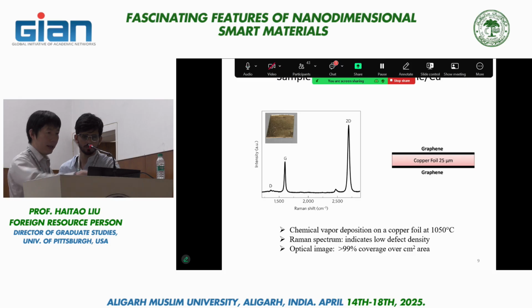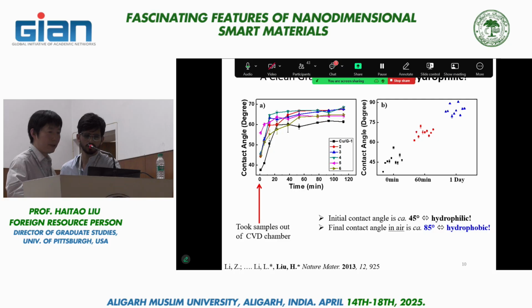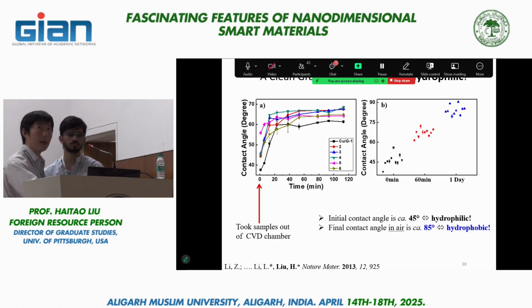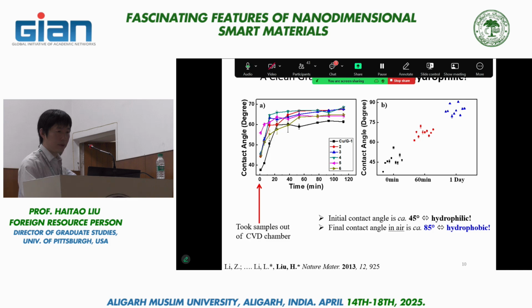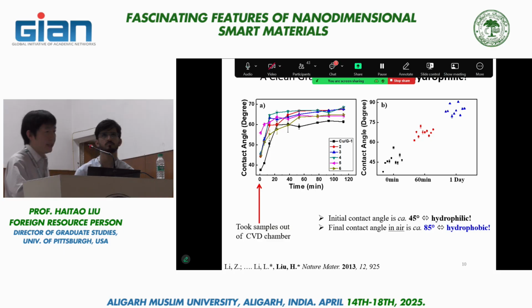So we grow the graphene on copper in a high temperature CVD setup. We cool it down to room temperature under hydrogen flow. We then take it out, and each graphene piece is about this large, so we can add a lot of water droplets. So what we do is we add a water droplet, measure the contact angle. After a couple of minutes, add a drop of water at another location, measure the contact angle, and so on and so forth.